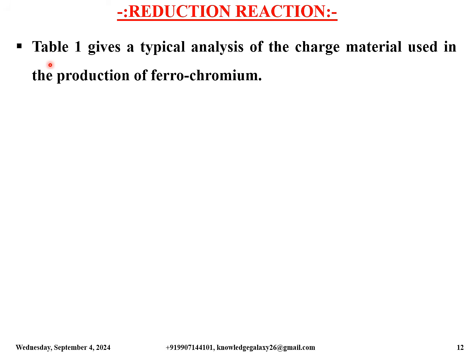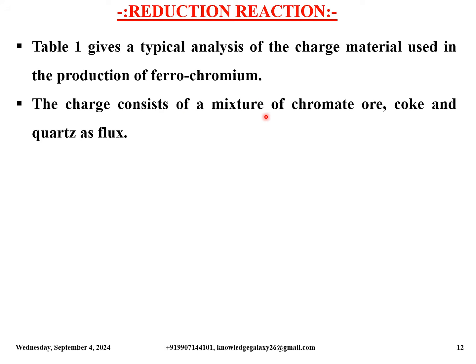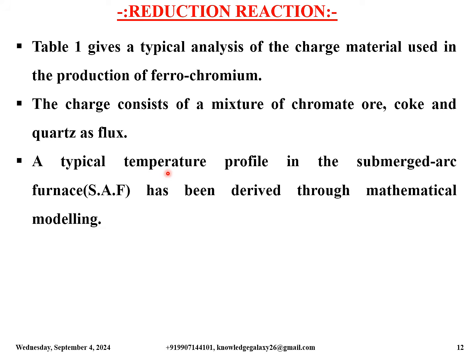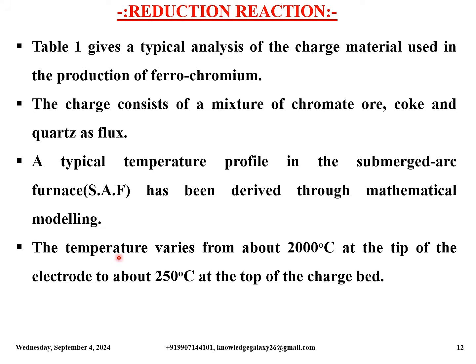Reduction reactions. Let us consider the different reduction reactions happening in the production of high carbon ferrochrome. Table 1, which is depicted in the next slide, gives a typical analysis of the charged material used in the production of ferrochromium. The charge consists of a mixture of chromite ore, coke and quartz as a flux. A typical temperature profile in the submerged arc furnace, that is S.A.F., has been derived through mathematical modeling. The temperature varies from about 2000 degrees Celsius at the tip of the electrode to about 250 degrees Celsius at the top of the charge bed.